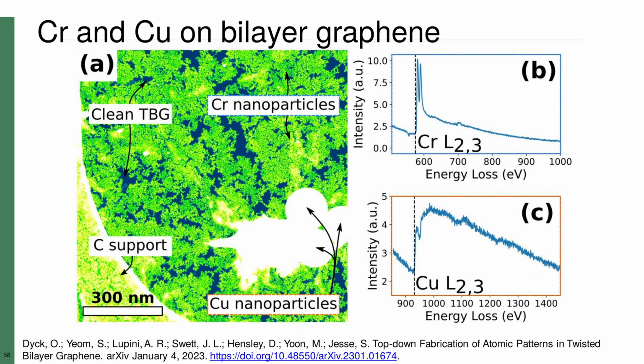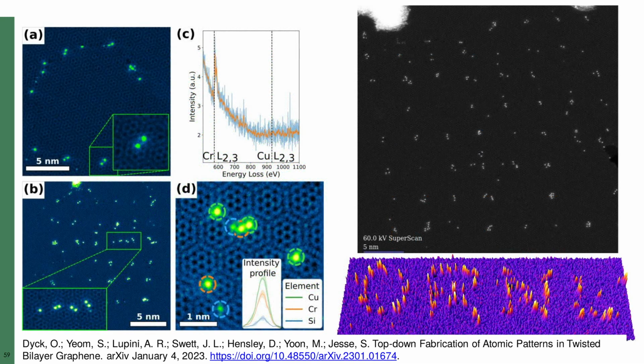The dark areas are clean, twisted bilayer graphene. The green nanoparticles that are all over the surface are the chrome, and a bit of foreshadowing, we also had a few spurious copper nanoparticles scattered across the sample. Then we heated everything up to around 1000 degrees Celsius and started to see impurity atoms spontaneously attaching to the graphene wherever we looked. We fired up the patterning platform, and we were able to start patterning atoms in small